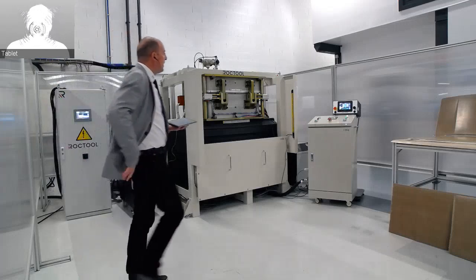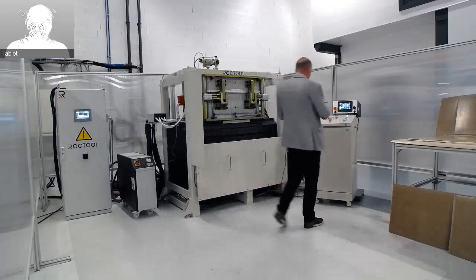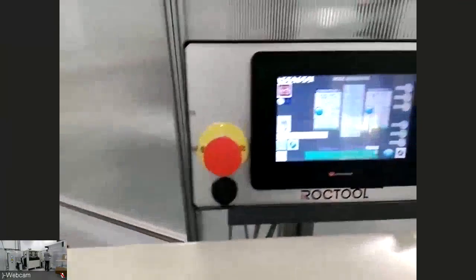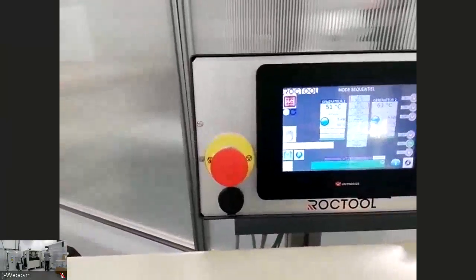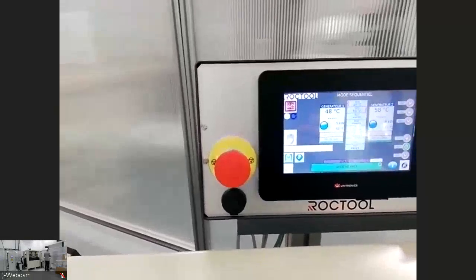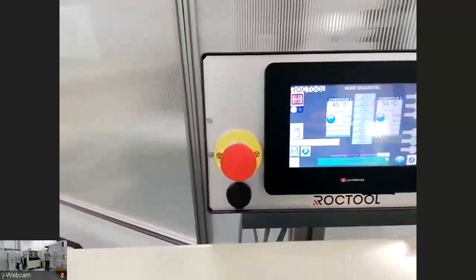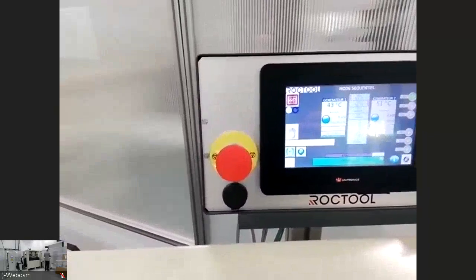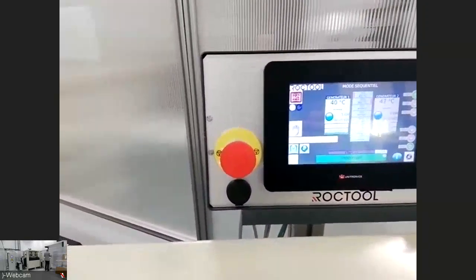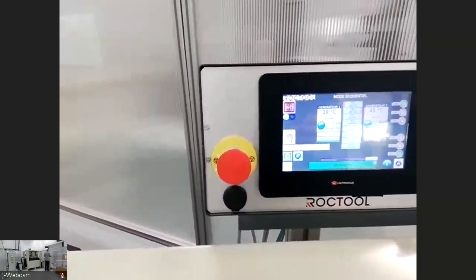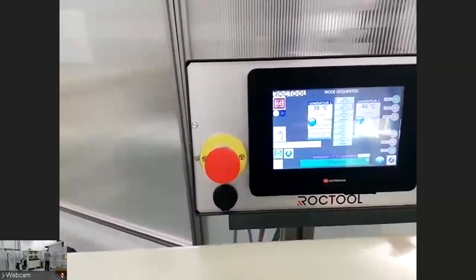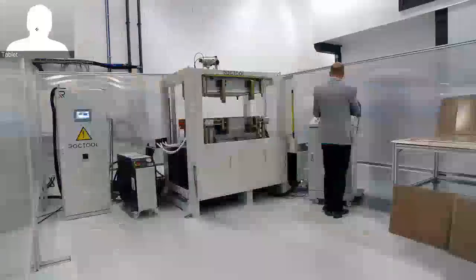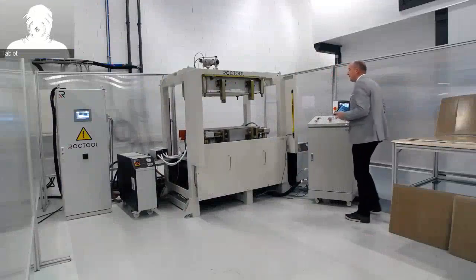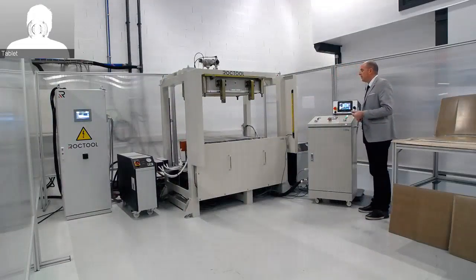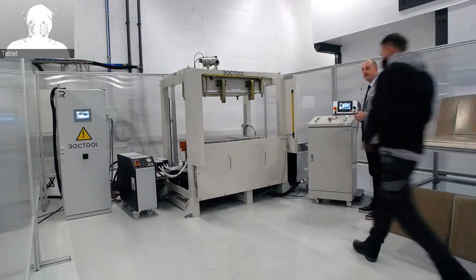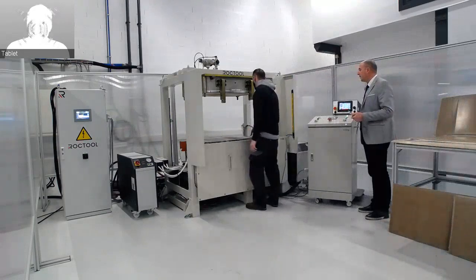Now we start the cooling step. So you see here, it's a very fast cooling. In less than 30 seconds, we go to 50 degrees from 200 degrees. And now we open the cell and we can demold the part.